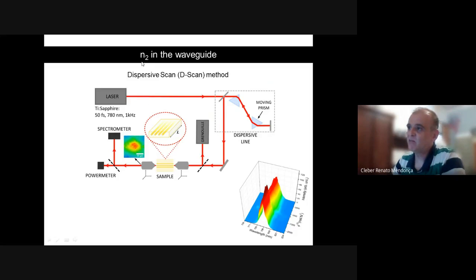So in order to study that, we actually perform this experiment here. I'm not going to go into details, but basically I have a stretcher of the pulse here. I take my 50 femtosecond laser pulse, I send it to this part of the setup, and by controlling the setup here, I can actually control the duration of the pulse. And then I couple that light, whose pulse duration I can control, in the waveguide, and I analyze the output of the waveguide, and how much nonlinearity I'm getting from my fabricated waveguide as a function of the dispersion of the pulse.